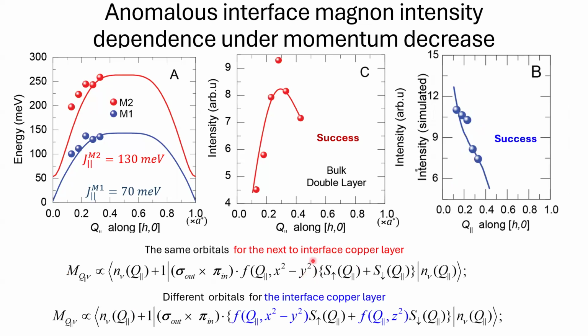Okay. So we see that we can describe very nicely the behavior of the intensity for the bulk-like magnon, but it completely fails to describe this intensity if we use the formula for the matrix element with the same orbitals. But the situation can be very easily resolved if we suppose that this destructive interference completely disappears, because we have one spin operator for spin up, for instance, with one orbital, and another spin down, let's say, with orbital z square.